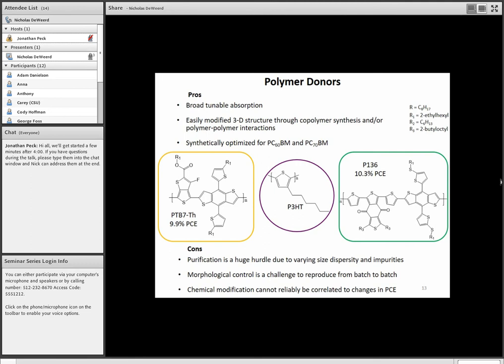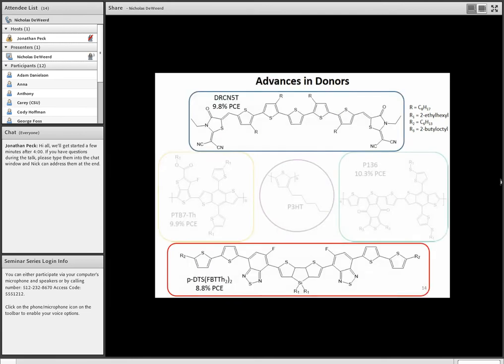You can get residual metals or size dispersity, meaning your oligomer chain length varies to a large degree, or if you have stereocenters and you don't have regioselective polymer control, all of those things have been shown, in general, to have a deleterious effect on device performance. So from a research standpoint, because of these batch-to-batch differences that you can have through small amounts of impurity changes, that makes reproducibility difficult, especially at the research level. But that's why I'm really interested in small molecule donors.